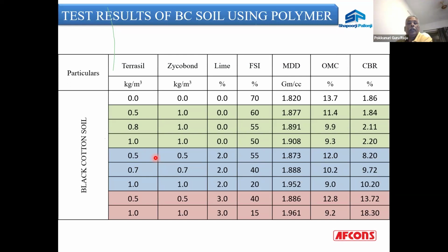This is a table which shows the test results at different doses of the chemicals. The first two columns, Terrasil and Zycobond, if you see, we have tried to do the testing at 0.5, 0.8, and 1 kg per cubic meter of soil to be treated. The top line, which is in white, is basically the untreated soil, wherein you can see that the FSI value is 70% and the CBR is 1.86. The 4 days soaked CBR we're talking about, and all these results are soaked CBR only.